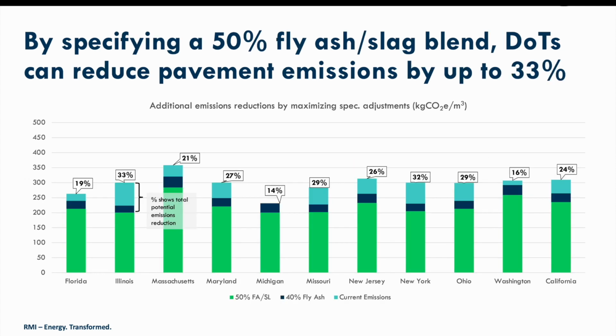Next slide. So how can we use this data to further reduce our greenhouse gas emissions? We see a graph with the same axes as before, states on the x, and kilograms of carbon dioxide equivalent per cubic meter of concrete on the y. Specification emissions can be reduced by up to 33% by making the switch to a 50% fly ash and slag blend. Next slide.